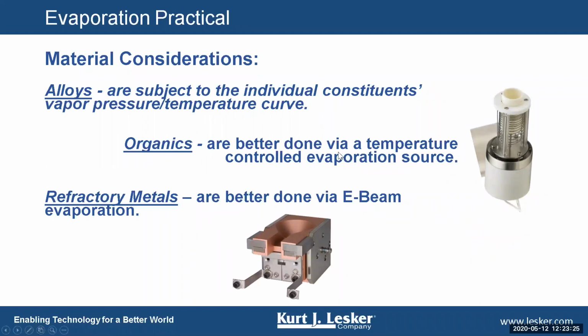Again, as we covered, organics are better done in a temperature-controlled source where you can apply power and monitor the temperature. There's a thermocouple inside these sources. The crucible sits on the thermocouple, and you'll be able to heat the source up based on temperature. Refractory metals, a lot of people say, hey, I want to resistively evaporate tungsten or tantalum or platinum or something that's a very high temperature material. Most of those are better done via E-beam, and some of them are quite impossible via resistive evaporation.